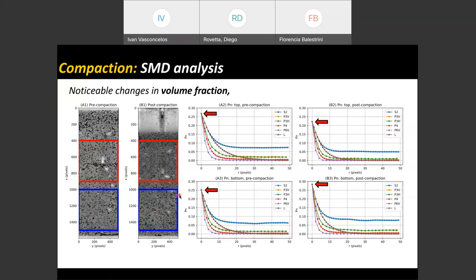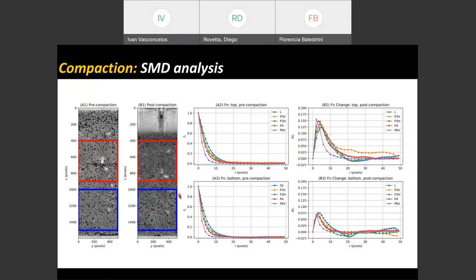Let's see how. Now remember, I said these curves, because of volume fraction, are difficult to compare. So we use those F curves that depend only on geometry and no longer on volume fraction. So now remember, they go from 1 to 0. And now we see the differences between before and after here on the right-hand side. Notice that in these first few distances here, at the top, we have a big bump. What this bump tells us is exactly by how much the pores have been squeezed. And the pores have been squeezed quite dramatically. That's what decreased porosity. We can also see from the orange line that anisotropy has also decreased.